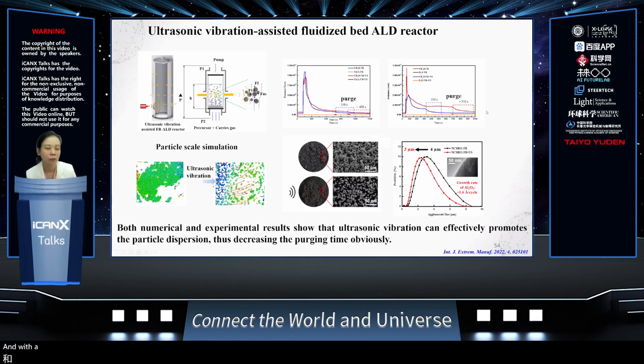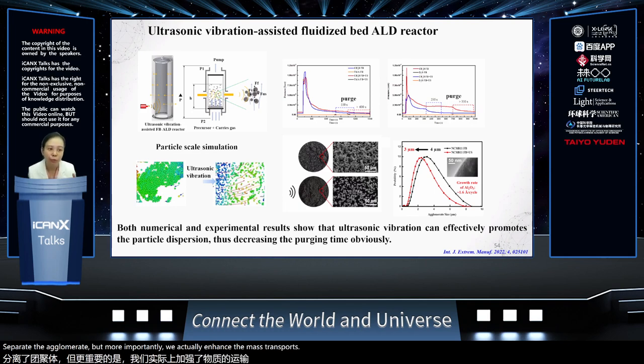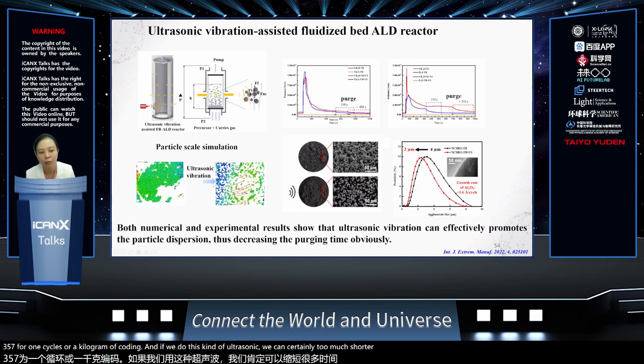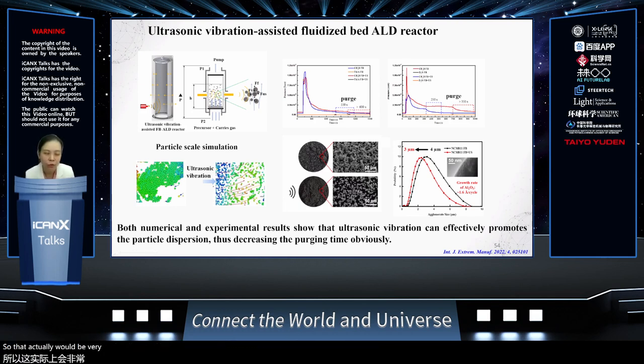And with the tuning of the ultrasound, we'll be able to separate the agglomerates. But more importantly, we actually enhance the mass transport. It would help us to shrink the process time significantly, as shown here. Without that process, we have to spend over 357 seconds for one cycle of a kilogram of coating. And if we do this kind of ultrasound, we can shorten it to a much shorter time. So that would be very beneficial, but eventually you have to know the surface reactions and the mass transport